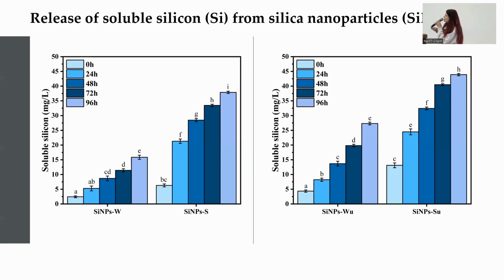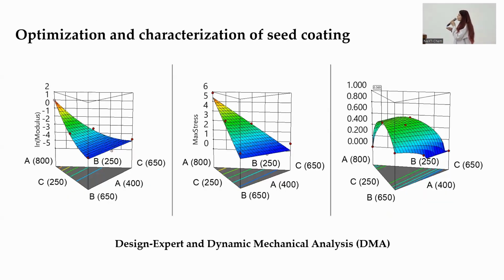We also wanted to assess the release of soluble silicon from silica nanoparticles, and we can see that the soluble silicon is released day by day constantly during the 4 days tested, and that the ultrasonicated nanoparticles release more soluble silicon than the non-ultrasonicated ones.